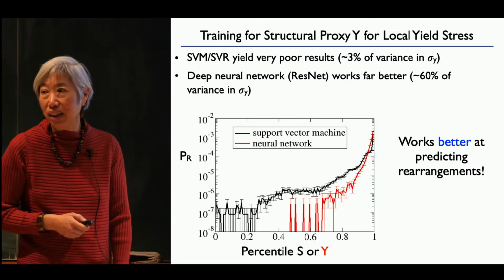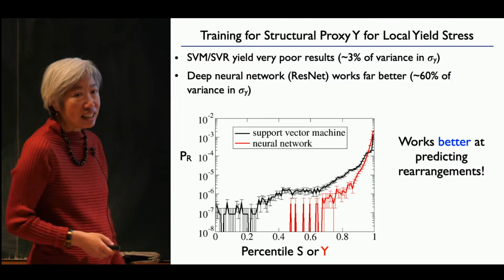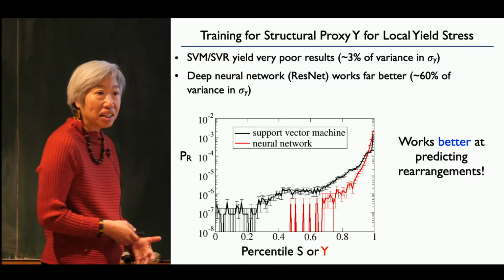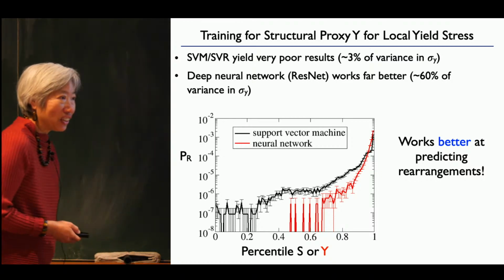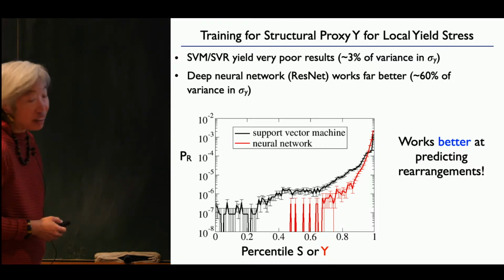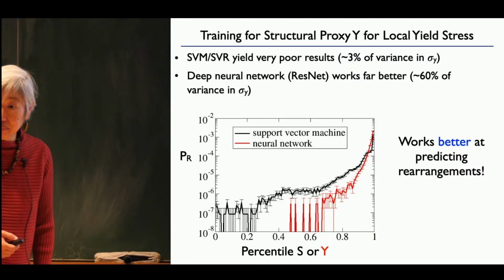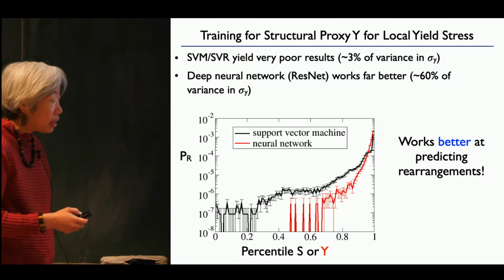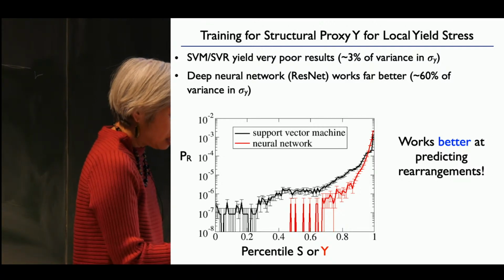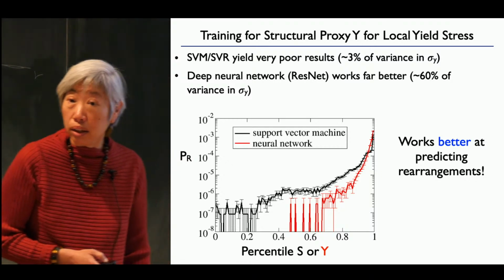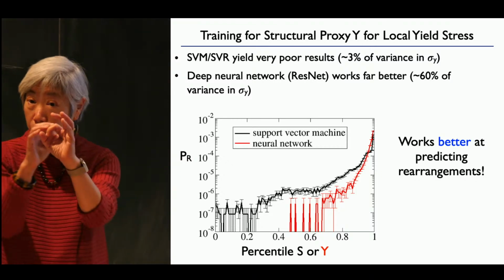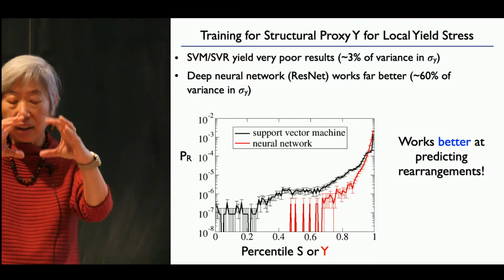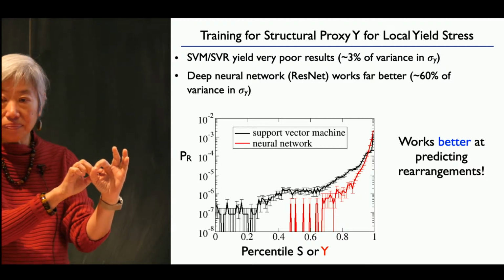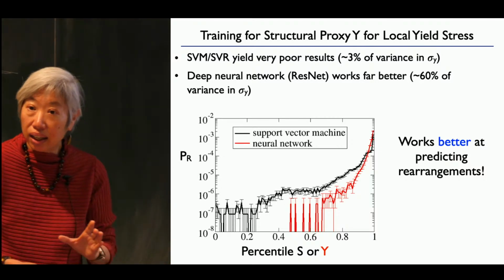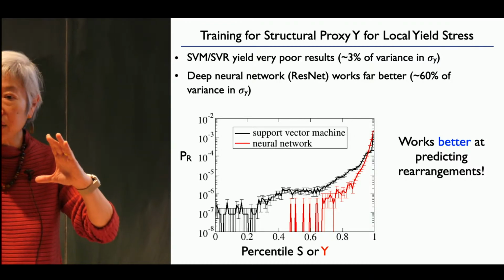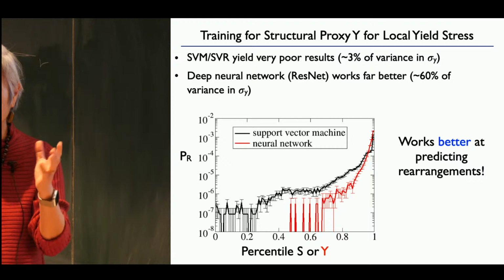And what we end up using is a neural network. This is ResNet. Okay, it's an ugly thing. I'm not defending it in any way except to say that it works quite well. And we were in a hurry. The input to the deep net is always delta squared min. We just feed it images of the particle and its little local neighborhood. The particle is always at the center, and its neighborhood is at a certain scale, about 5 particles across.